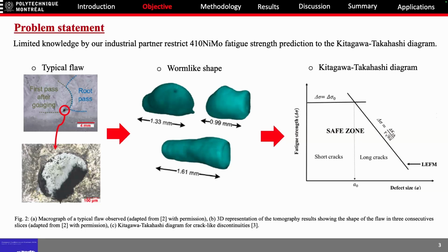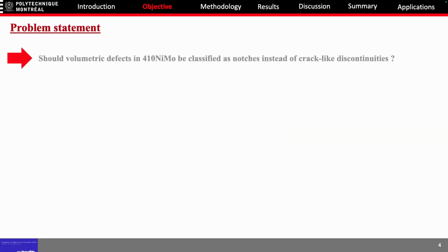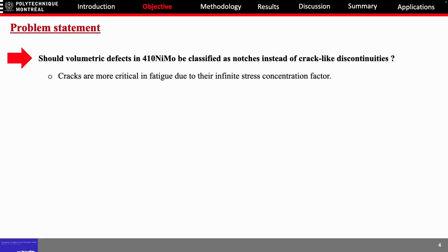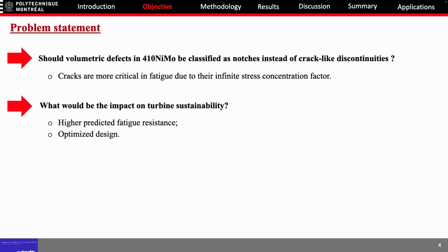Basically, it is a prediction of fatigue strength as a function of defect size, and we use the LEFM, linear elastic fracture mechanics, based approach to predict the fatigue resistance. So, should volumetric defects in 410 nickel molybdenum be classified as notches instead of crack-like discontinuities? Cracks are more critical in terms of fatigue due to the infinite stress concentration factor. And what will be the impact on turbine sustainability? Higher predicted fatigue resistance, and it optimizes the design.